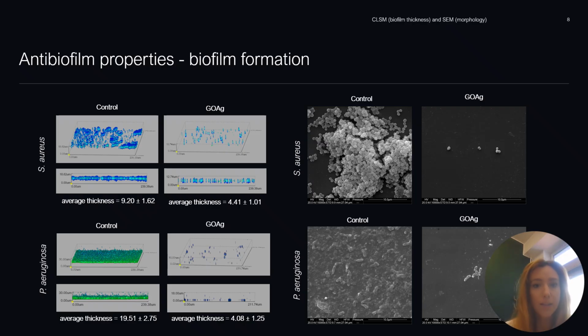groups with the nanocomposite. These findings were further confirmed with scanning electron microscopy observation. In the control sample, bacteria formed a dense three-dimensional biofilm structure with extensive cell-to-cell interactions in case of those two bacteria. In contrast, in groups with nanocomposites, samples exhibited a dramatic reduction in biofilm coverage. The biofilm architecture was severely disrupted, and only isolated bacteria cells or small cell clusters, for example, here, were observed